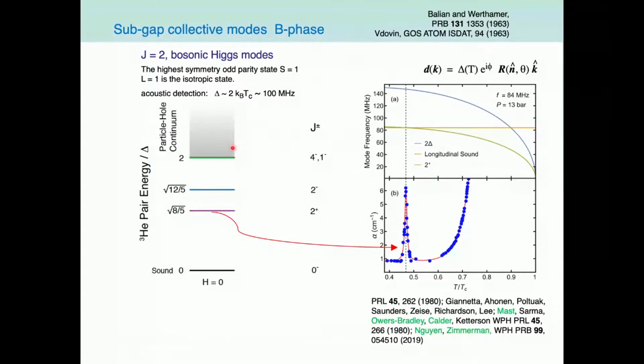subgap states. Here I'm showing on the left-hand side that the gap of 2 delta per Cooper pair has 2 subgap states at sort of magic numbers of square root of 12/5 and square root of 8/5. That was calculated specifically by Vdovin, and it was calculated in what's called weak coupling theory. And furthermore, it was identified that the total angular momentum is a good quantum number for the B phase, again neglecting the dipole interaction, and that in particular, these subgap states have total angular momentum 2.